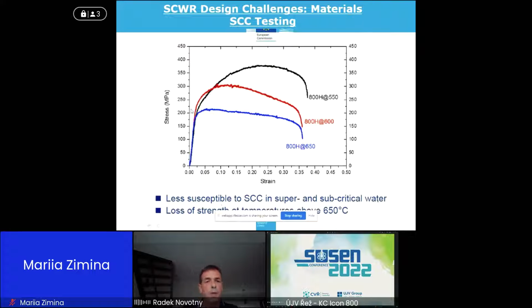But what is very important for us is the change of mechanical properties. We can see big decreases in yield strength, maximum stress, and also in ductility, not so much in ductility, but definitely in these. So the discussion is to what extent, because we are using data from mechanical tests at temperature, usually in air or in inert environment, but how relevant are these data when the components are actually exposed to real environmental conditions of supercritical water? This needs to be answered, and in this area we need to compare to data from mechanical tests in air, and do the same test in the environment.